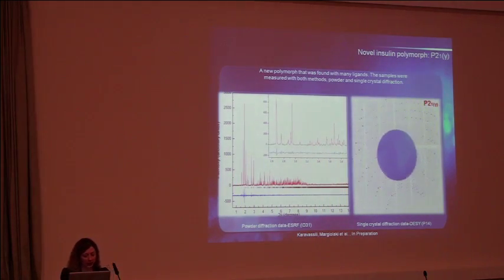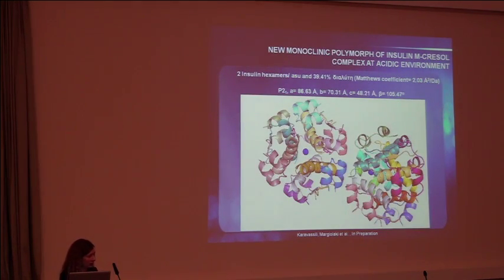What we did gradually, we used the powder data for this new phase and single crystal data collected very recently at DESY in Hamburg. We visited DESY from the BioStruct-X program, and we solved the structure using the molecular replacement method. So it's a new polymorph that we believe has pharmaceutical interest, and at the moment other parameters such as toxicity and physical-chemical characteristics are studied in the collaborating pharmaceutical industry.